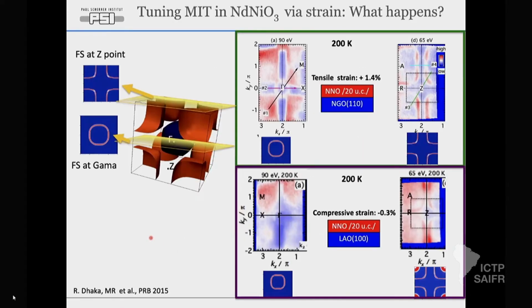Now what I wanted to say is that the electronic structure of all these systems in that class of materials is composed of cuboids, which are hole-like, and in the middle, at the gamma point, you have some kind of globe-like electron pockets. If you do cuts at the gamma point, the Fermi surface will look almost like a circle. When you do this at the Z point in the Brillouin zone, the Fermi surface will look like a cross-like structure.